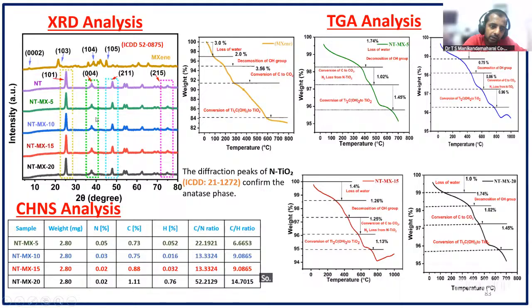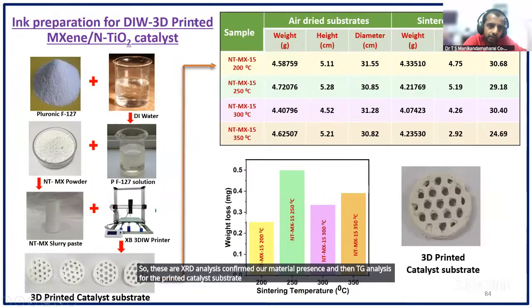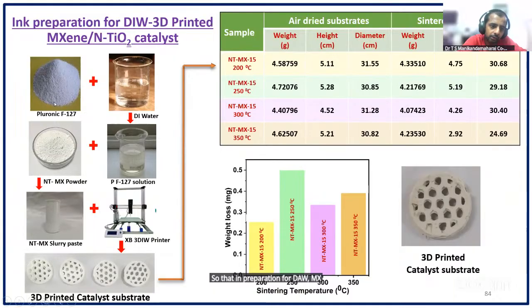These are XRD analyses confirming our material's presence, and then TG analysis for the printed catalyst substrate. For ink preparation for DIW, the MXene and NTiO2 catalyst, we prepared a solution with Pluronic and added the NTiO2 MXene powder. With that slurry loaded, we printed the catalyst substrate. This is the as-dried substrate, then the sintered substrate weight. We weighed and compared it. And this is the weight loss of the material with varying sintering temperature, 200 to 350.